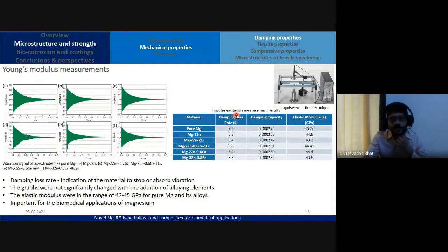So using this technique, apart from your typical tensile test, you have a non-destructive method of calculating the Young's modulus. With this, we could find that the Young's modulus did not change much with the addition of alloying elements, which is good because we do not want too high a Young's modulus. We want it to be in the range of 43 to 45 GPa for magnesium and its alloys.